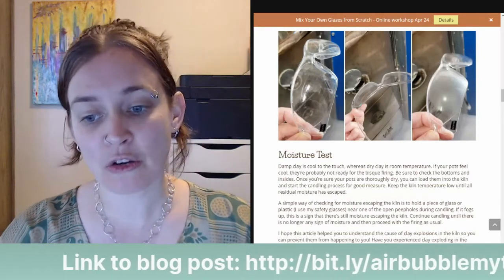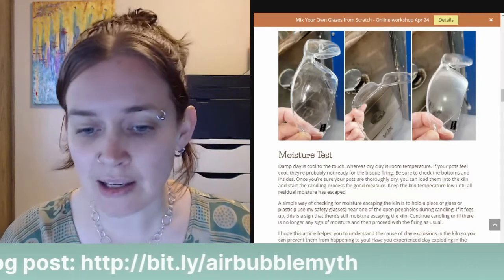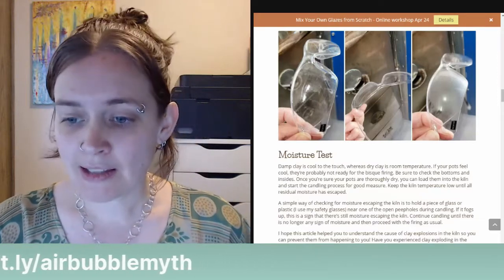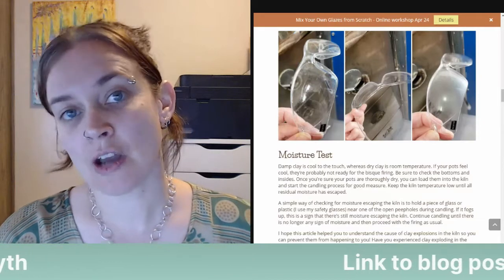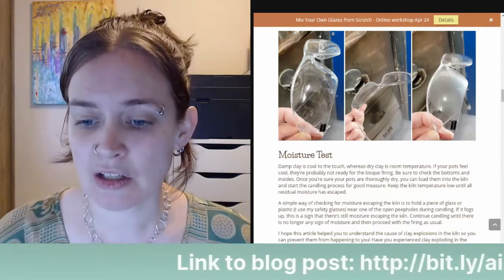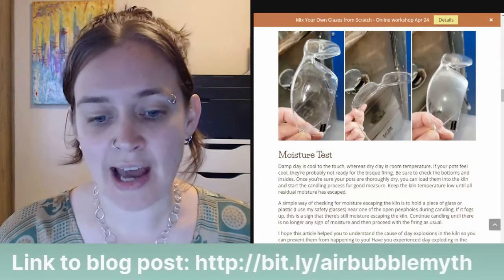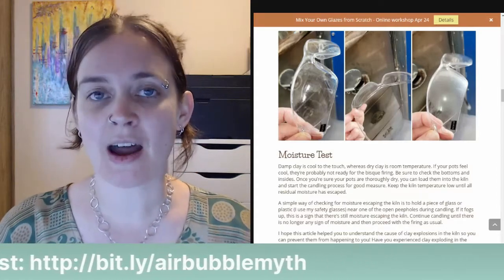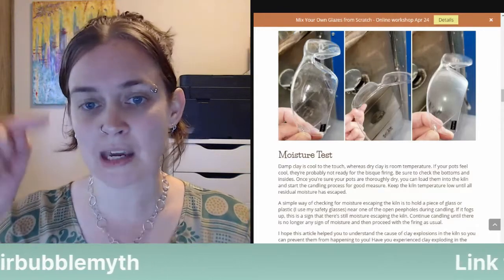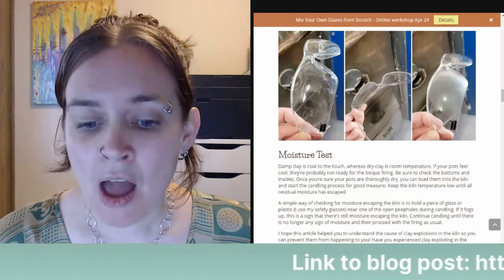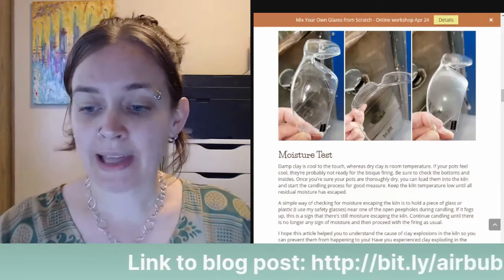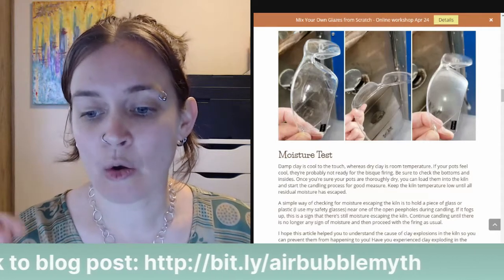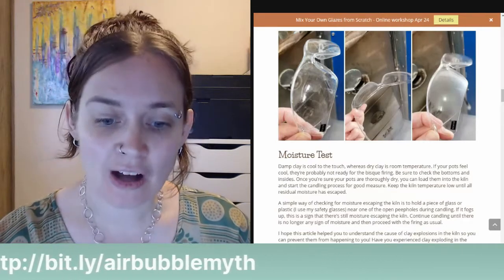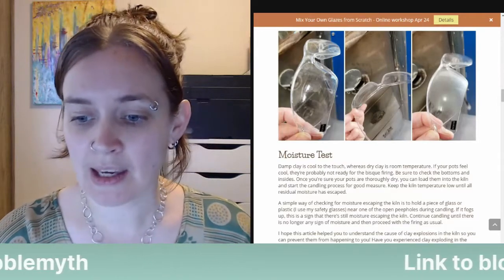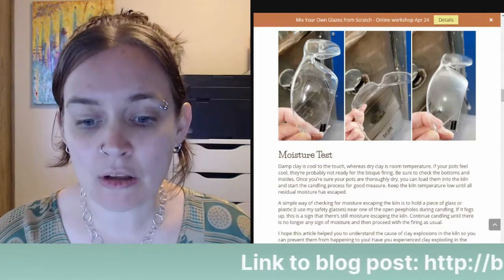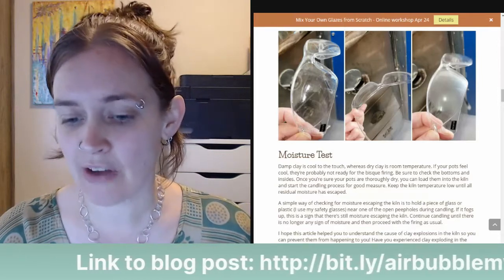Once you're sure your pots are thoroughly dry, you can load them into the kiln and start the candling process for good measure. Keep the kiln temperature low until all residual moisture has escaped. A simple way of checking for moisture escaping the kiln is to hold a piece of glass or plastic. I use my safety glasses, but I've also used a little mirror in the past. Whatever's handy. You place a piece of glass or plastic near one of the open peepholes during the candling. If it fogs up, this is a sign that there's still moisture escaping the kiln. Continue candling until there is no longer any sign of moisture, and then proceed with the firing as usual.